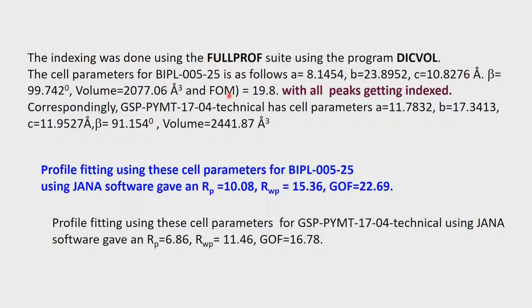What is very important is this: all the peaks have to be indexed. When you do a profile refinement, it is your job to make sure that all the peaks which appear are indexed — meaning every peak has an HKL associated with it. There must be no unindexed peak in the list used to determine the unit cell dimensions. When that condition is met, we know the unit cell has been very uniquely determined for the system.